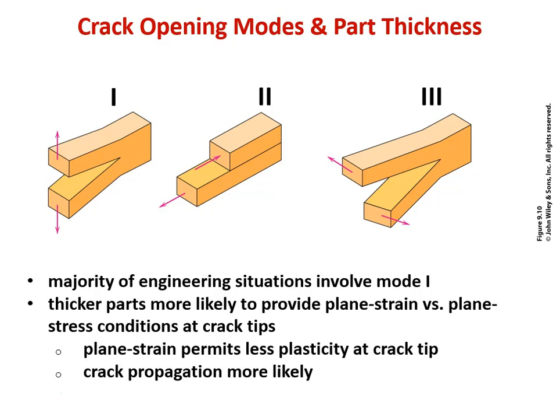And the other default worst case scenario, of course, is the higher level of constraint, which is called plane strain. That merely means that your material is thick enough that you're likely to encounter a triaxial stress state at the crack tip. So it basically means you had a fairly thick piece of material, which is typical for most tensile specimens. If you had a real thin material, that would be plane stress. Great for application, but if you're testing, you want to do a test that captures the worst conditions you're likely to see in the field.